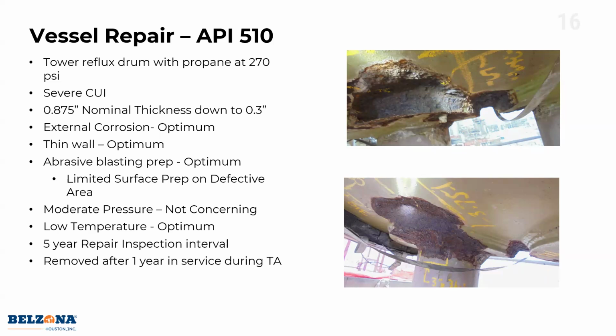However, and we see this all the time, they did not want to prep the badly pitted areas because this was done with a live vessel, a live drum. So this was live at 270 psi with propane. They didn't want to take the chance that there might be a tiny pinhole that might pop open once you blast this. So that area is a compromised area. However, we are going to extend our blast a little bit further. We're going to cover that area with a surface tolerant material and let it dry.